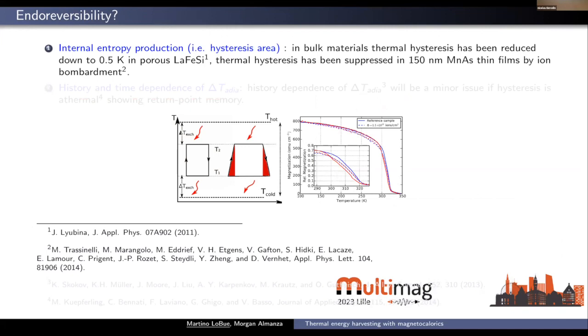Okay. Now let's say yes, but we said that we are reversible inside. But this is true, for instance, for most magnetocaloric materials. Well, caloric effects are common to all polarizable systems, but they are huge and interesting near the verge of a ferroic transition. Okay. If the transition is second order, no problem. But very often, magnetocaloric materials show a transition of the first order with thermal hysteresis. So you risk having internal dissipation indeed. First order transitions are very good because you have latent heat that is enhancing the effect, but you may be in metastable states and so out of equilibrium.